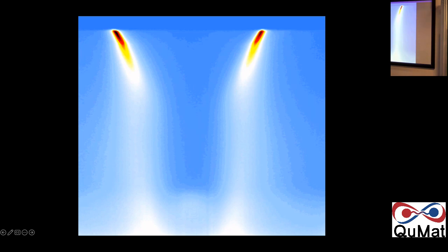There is no known material that has delta functions as its spectral function. Maybe you could argue for a very pure sample of gold or copper, or maybe even better sodium, which is just an s-electron metal. The one right at the Fermi level for a perfect crystal, which of course doesn't exist, could be a delta function if you had a perfect spectrometer, which you don't. But in all of these cases, the growth of the width as a function of frequency is often not omega squared and T squared. Here you have something growing as a function of omega as we go down, in a way which looks like a power law.